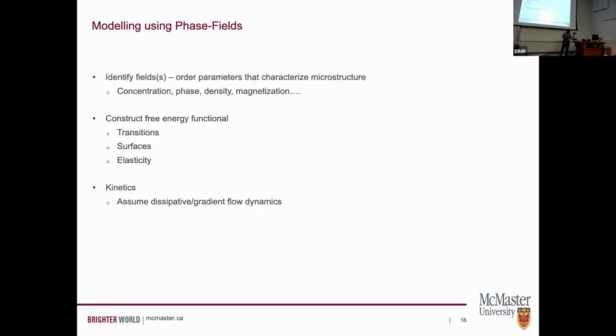So phase field models. Phase field models start off being very toy, niche models that the physics community, particularly condensed matter, use to look at simple phase transitions. And then some people in materials got a hold of it, and we realized actually it's not that bad at examining microstructure as well. And so the idea of phase field models is initially what you want to do is identify the fields of interest that you care about in your system. So is it density? Is it concentration? Is it the phase? Is it the structure? Once you've identified this, you assume, at least at the microstructure level, that it's constant, except for where you have interfaces and surfaces.